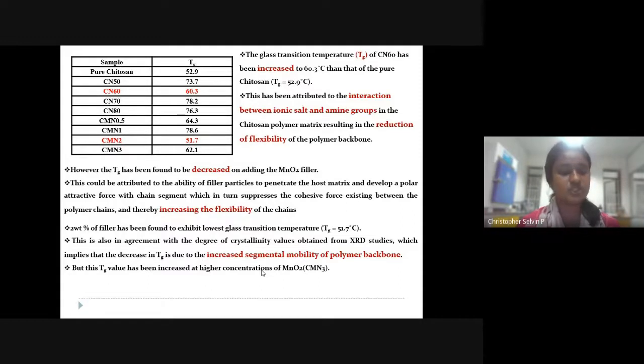This is because of the ability of the filler particles to penetrate the host matrix and develop a chain segment, which in turn suppresses the cohesive force existing between the polymer chains and thereby increases the flexibility of the chains. The polymer with 2 weight% filler shows the lowest glass transition temperature, which is about 51.7 degrees Celsius. This is also in agreement with the degree of crystallinity values obtained from XRD studies, which implies that the lowering of the transition is due to the increased segmental mobility of the polymer backbone. However, the transition value is found to be increased at high concentration of the filler.